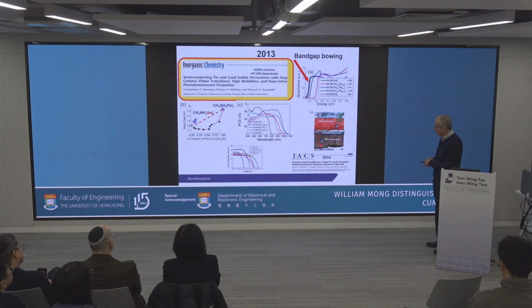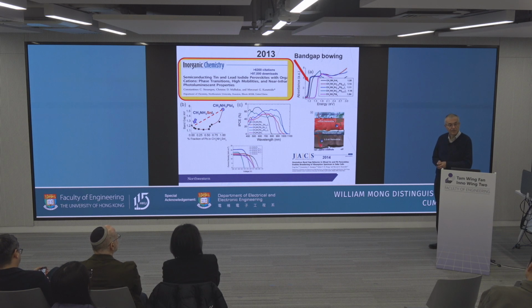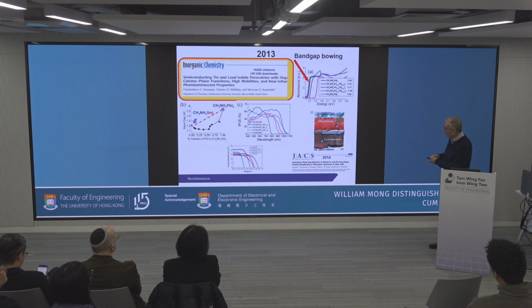This became the foundation of tandem cells, because in tandems, if you want to get 35, 40, even 50% efficiencies, the future direction of perovskites is tandems. You need to have two cells, maybe even three. A wide gap perovskite that captures part of the light, the rest of it goes through. A narrow gap captures the rest of the light. And together, the efficiency is much higher. It's the way to 35 and 40%. But you need this narrow gap bottom perovskite, and you can make it narrow by mixing lead and tin. So this became also a key discovery.